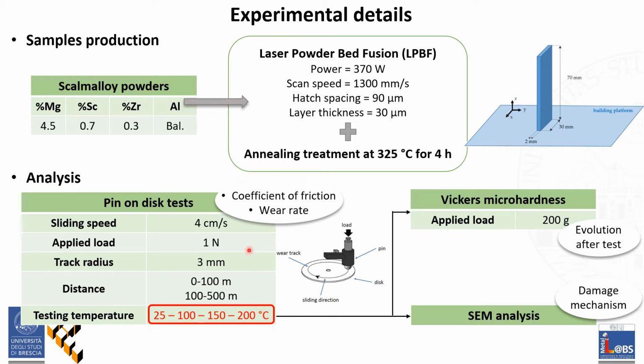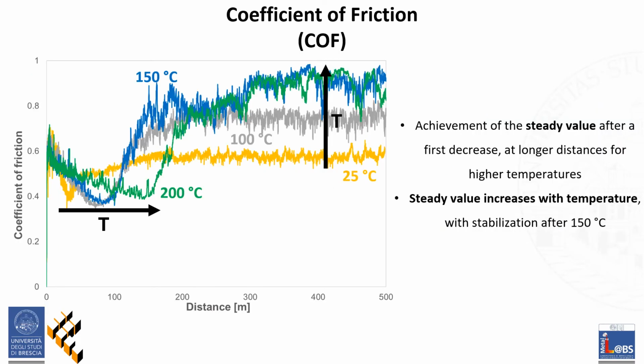Every test was stopped at 100 meters and concluded after 500 meters of sliding distance. Coefficient of friction was determined and wear rate was calculated both for 100 meters and 500 meters of sliding distance. Microhardness was evaluated to monitor microstructure evolution after temperature maintaining. SEM analyses were performed to identify the damage mechanism. Results will be now presented.